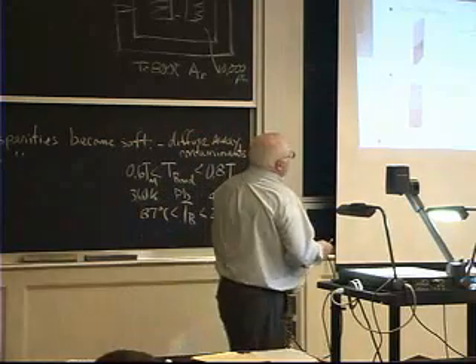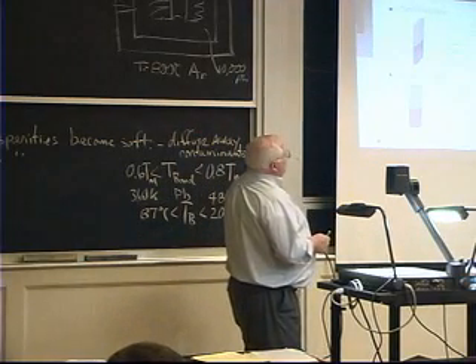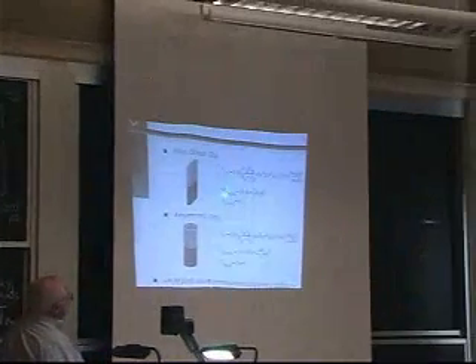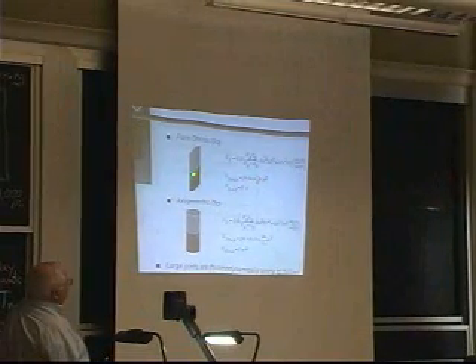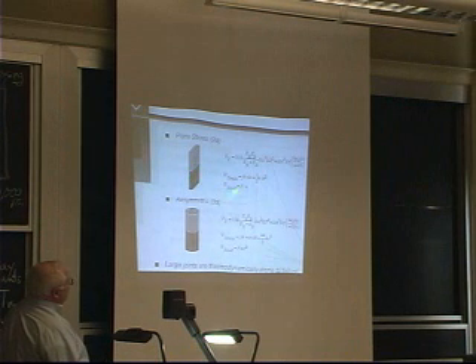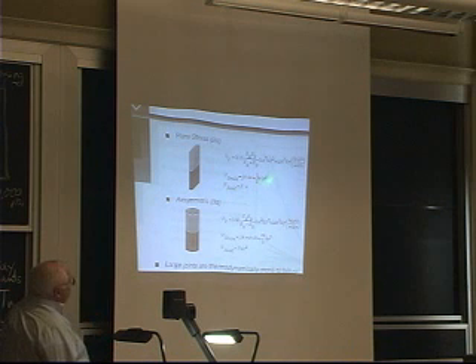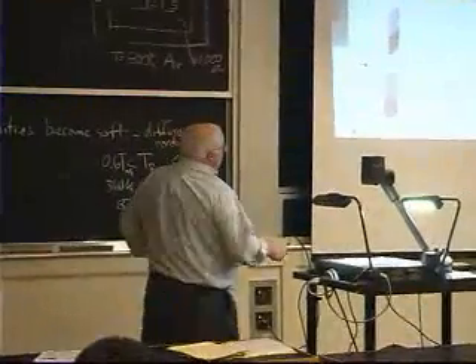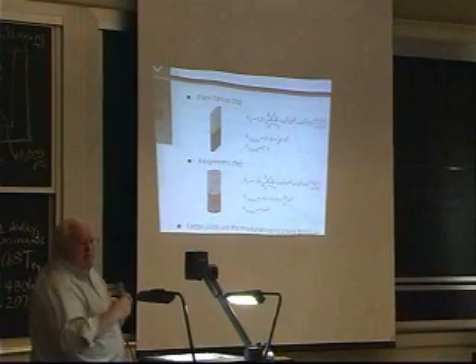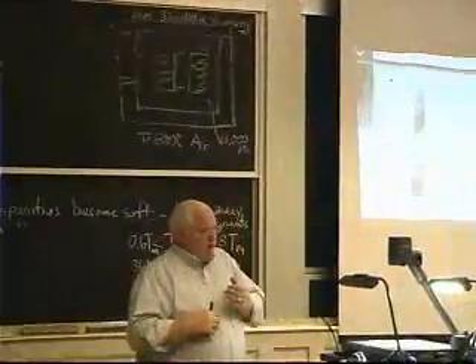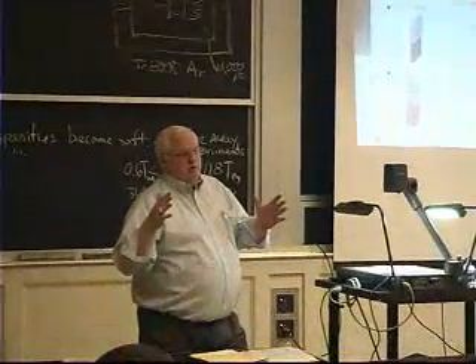Well, it turns out, if I look at the strain energy for bonding, there's a formula like this for plane stress. The strain energy goes as the width x squared, but the bond strength only goes, if this is unit depth, only goes as the width x. So if the residual stress energy goes as x squared, and the strength of the bond only goes as x, as the part gets bigger and bigger, I get bigger and bigger residual stresses. Okay? And even if I do it axisymmetric, it turns out the strain energy goes as r cubed, and the bond energy goes as the area, r squared. You always have one extra dimension to your energy as compared to your bond strength. And so larger and larger parts have more and more residual stress.